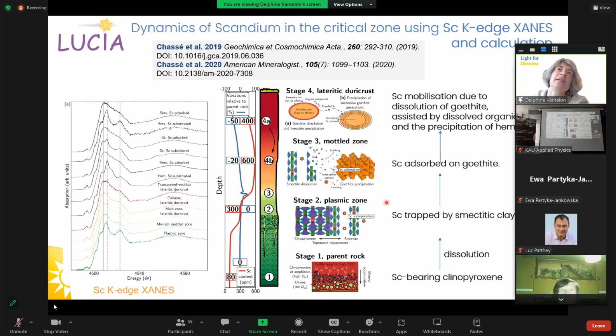Yeah, so in this case, on geoscience, our users wanted to study the evolution of the scandium speciation during the alteration process in a profile depth from the parent rock to the surface. So they collected samples at different depths of the profile, and they measured the scandium K edge XANES, and they used them as a fingerprint to follow the modification of the scandium speciation and its evolution with alteration.